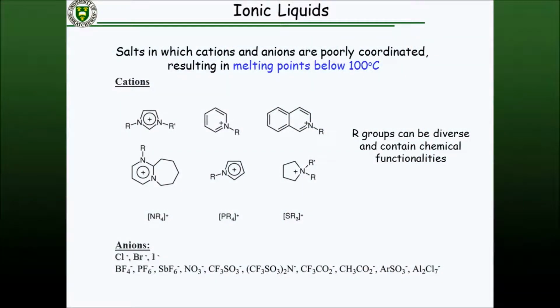Okay. Let's switch then to this idea of ionic liquids, and we moved into this when we first started in Saskatchewan in 2005. There were reports of people being able to make metal nanoparticles for catalysts, and they called them so-called naked nanoparticle surfaces in ionic liquids. And we were kind of curious about these types of systems. You have non-volatile solvents, the possibility of stabilizing nanoparticle catalyst, and the idea you could bring a substrate in, do a reaction, pump the substrate off or boil the substrate off, but then you can continuously reuse potentially the catalyst system. And there's all kinds of ionic liquids out there. I'm going to talk about a couple in particular, and that is the imidazolium system as the cation.